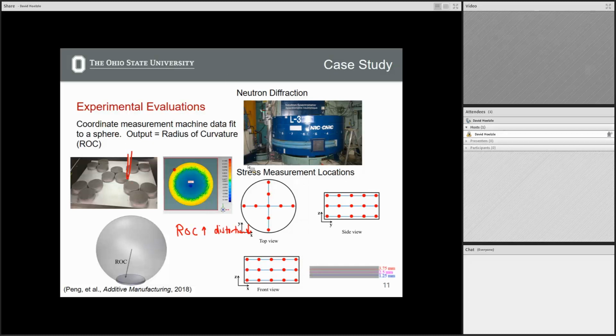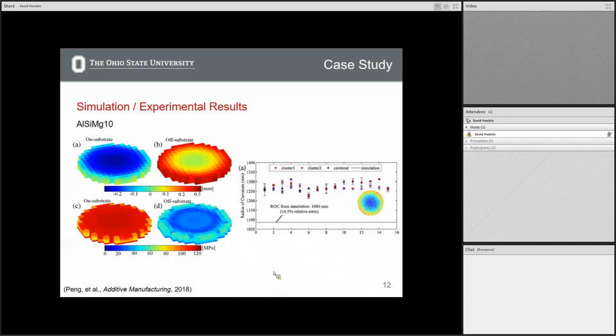Anyhow, so this was measurement. We were taking measurements of the residual stress in the part, both on the build plate and actually after it's been released at these locations. So this is different locations on the top surface and also different locations within the depth of the part here. All right, so we did both simulations and experimental results, so I'm just going to run through some of these here. Help orient you to what's going on here.